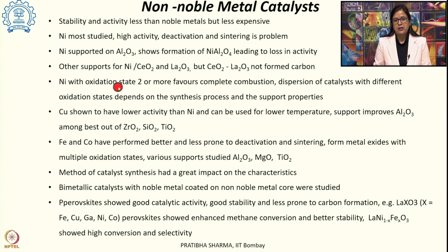Nickel exists in various oxidation states, and any oxidation state of 2 or higher favors complete combustion rather than partial combustion. So in the dispersion, how it is dispersed with different oxidation states, how it is synthesized, and what the support properties are all affect the activity of the catalyst.